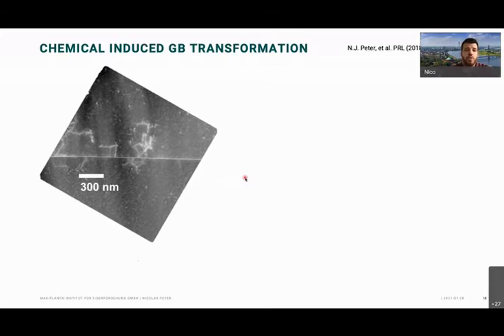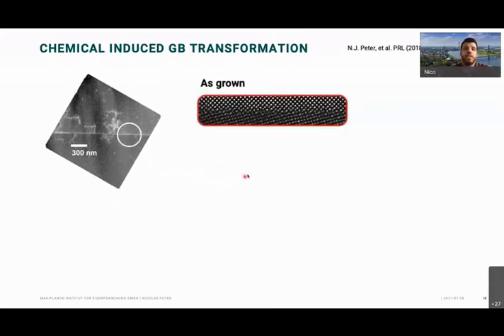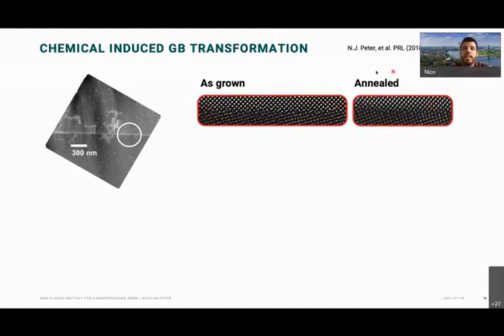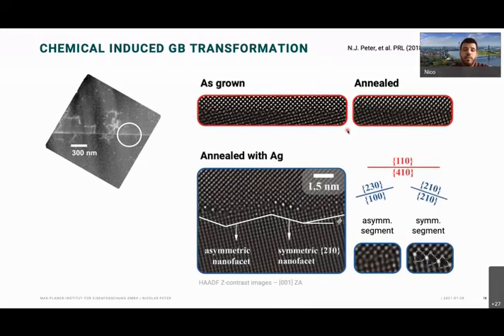But if we zoom in now to atomic resolution, we see the as-grown state is still fairly flat. It has a little roughness, but overall we call that a flat boundary. The annealed case is pretty much the same. Nothing changed really. So annealing without chemistry being involved doesn't really change much. But if we then introduce silver, we do see pronounced faceting occur. And this is shown here.